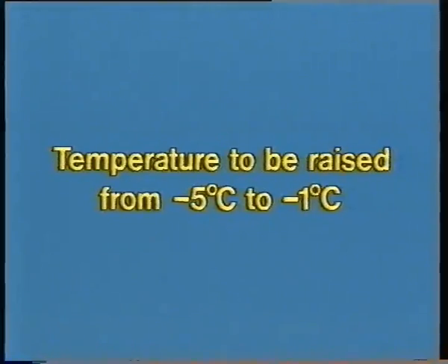If the sample is annealed after deformation, that is, subjected to a sudden rise of temperature from -5 to -1 degrees, then this enhances the mobility of the grain boundaries. The temperature rise we will now see occurs over a period of 2 hours and will be maintained at -1 degree for 5 hours. Pre-existing grains in the deformed aggregate act as nuclei and grain boundaries sweep rapidly through the grain aggregate. These replace the smaller deformed grains with large undeformed grains with smooth boundaries, equant grain shapes, and with boundaries meeting at triple junctions.